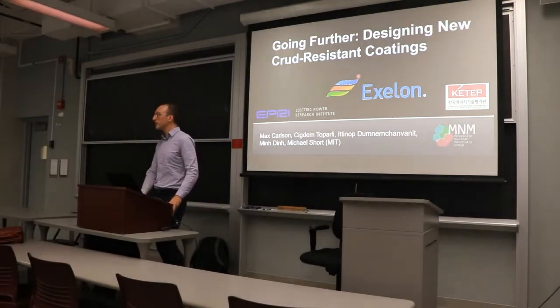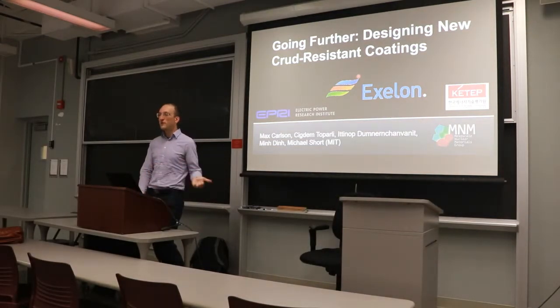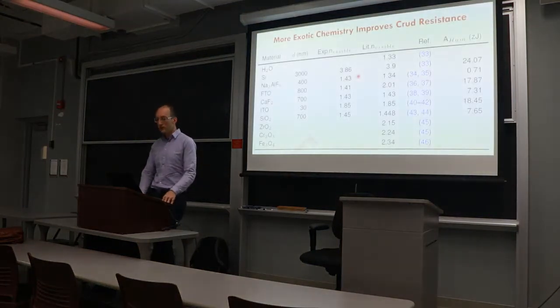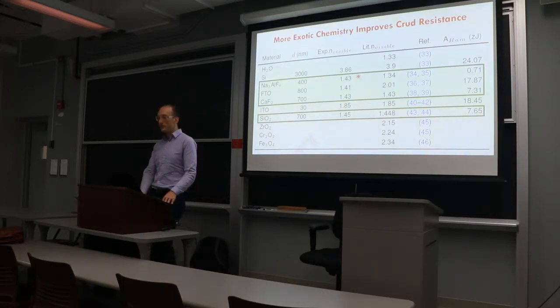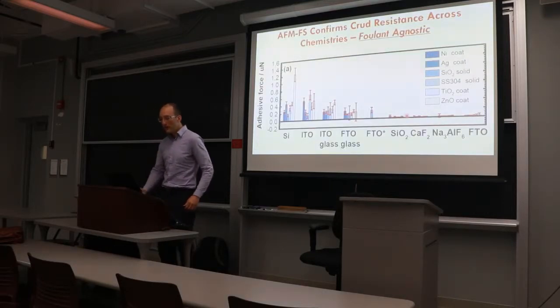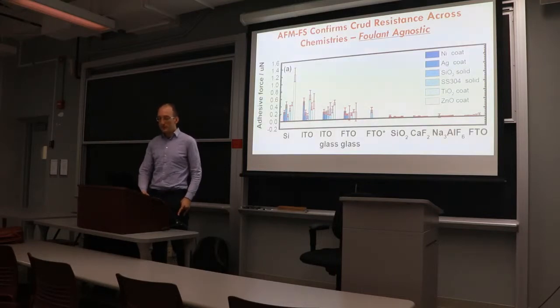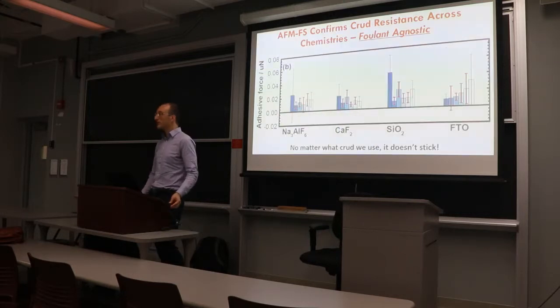But we can go a little further with this optical design principle, because industry may be happy, but the scientist in me says, how low can you go? So we started looking at some fluorine-based coatings, which have very similar optical properties to that of water. If you just look here at the visible index of refraction, that between water, cryolite, calcium fluoride, and even crystalline silica are really close. So we tried using those coatings and compared to some silicon substrates, glass substrates, an indium tin oxide heater that we happen to have lying around. These ones were off the chart. In fact, they were so slick that some of the error bars crossed the x-axis.